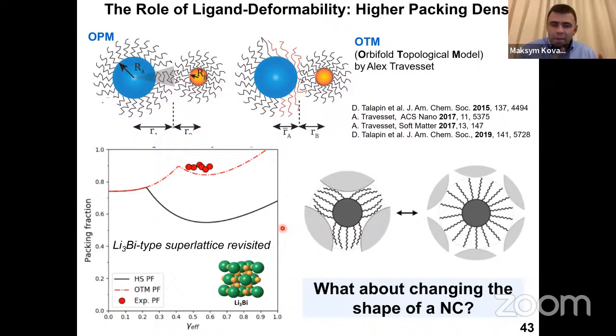your attention to the fact that your ligand shell is not only deformable, but it can deform in a very specific manner. And that was observed years ago and was invoked to explain the stability of some of the binary all-sphere assemblies, which would otherwise be hard to explain. So what can happen is that when two spheres approach each other, the ligands on the smaller one can bend away, can create these vertices, and therefore they can allow a more compact lattice so that these two spheres can approach each other closer when one of the spheres can bend away their ligands. And so this is stabilizing the higher packing density.